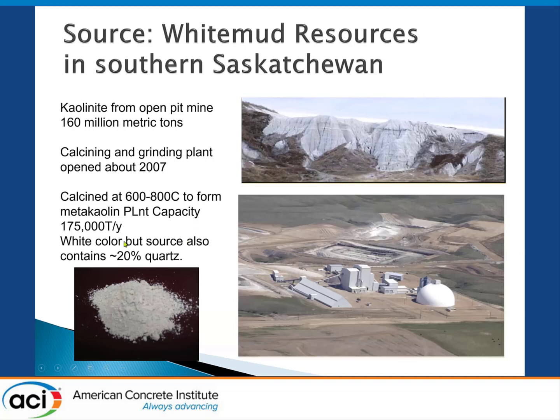It's a bit off-white, but it has about 20% quartz in it. It's not pure; it's in the order of about 80% pure, although I think later on they were able to remove more of the quartz. The sample we have dates back to when it was there.